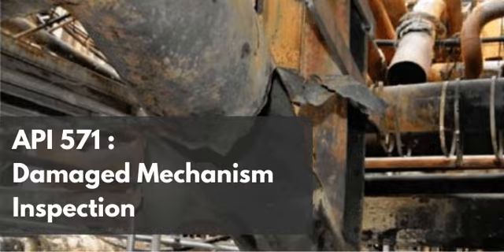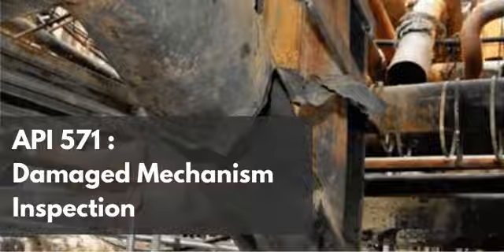Wait, so the chromium is still physically inside the pipe, right? Physically, yes. But because it's now locked hands with the carbon to form this brittle carbide molecule, it can no longer do its original job. Precisely. Because the chromium is now locked up in these new brittle structures, it is no longer freely available in the surrounding metal matrix to fight off corrosion or oxidation. The steel is literally being robbed of its defensive shield at the microscopic level. The surrounding matrix becomes chemically impoverished.